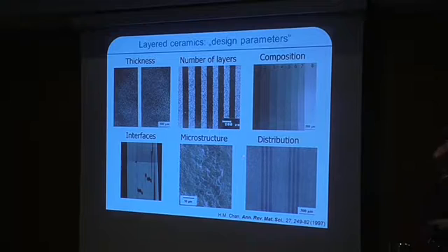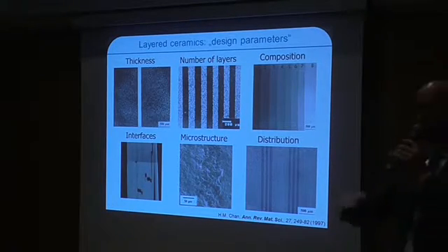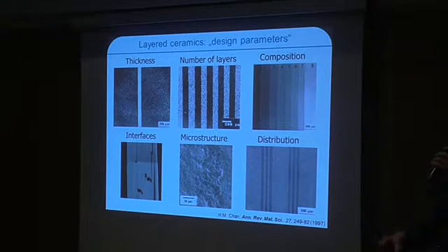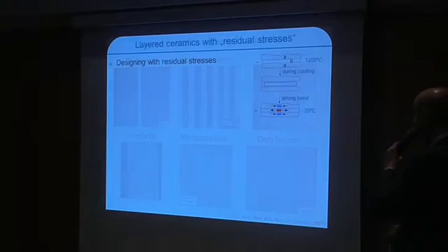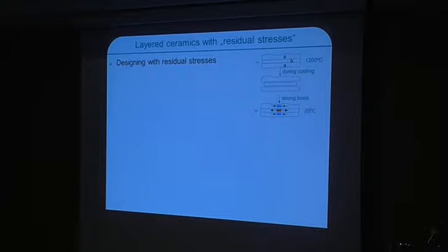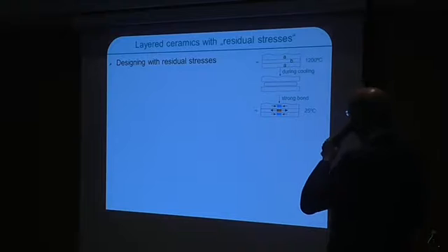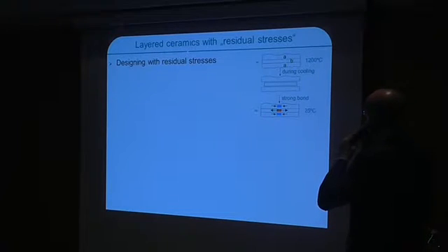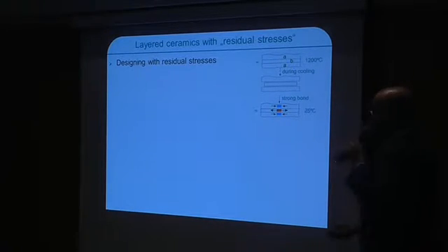So I said before that there are several possibilities. I will not go into that. Very important is when you ask the question, do you want to have a weak interface or a strong interface? In our case, you think of an application, you would not want to have a piezo actuator which delaminates or something like that, so we want to keep this kind of integrity. So we're thinking, what can we do to increase the mechanical properties, the crack resistance, for instance, of these systems? So we would say we can try to play with residual stresses.